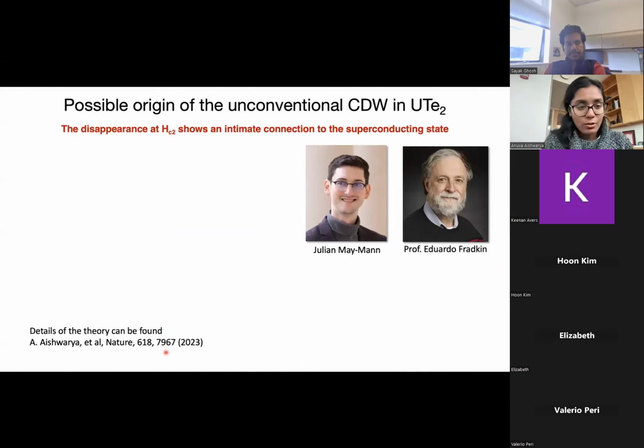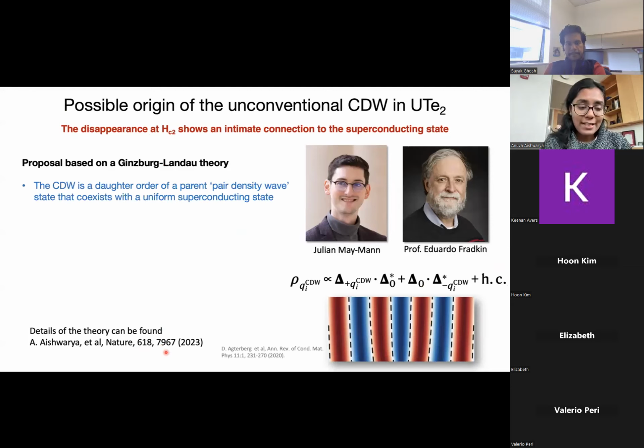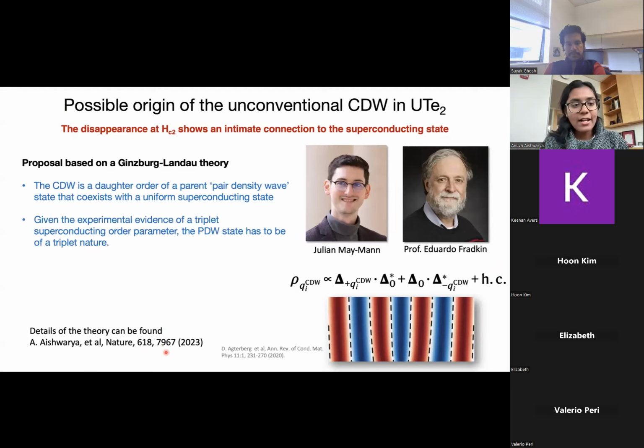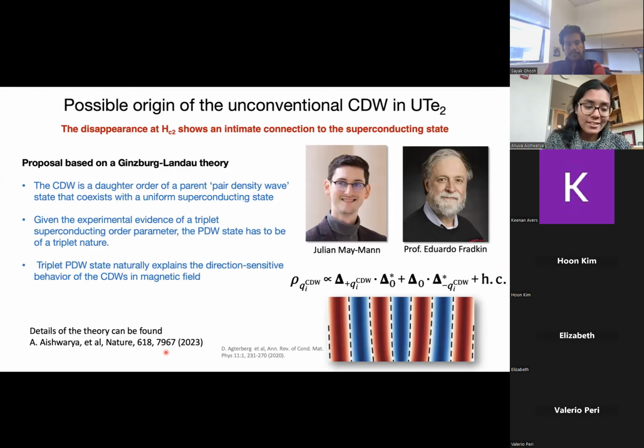The proposal is, so the disappearance at HC2 shows that the CDW and superconductivity are connected. So what we propose is that the CDW is actually a daughter order from a pair density wave state that coexists with uniform superconductivity in this material. And that given the evidence of a triplet order parameter, it's likely that the CDW inherits this triplet character, and that would naturally explain the direction sensitivity and the behavior in magnetic field.